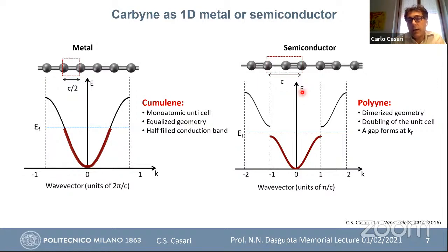In the other case, you have the possibility to have an alternation of single, triple, and so on bonds in a sort of dimerized chain. Now you have two atoms per unit cell, and by solid-state physics reasoning, you can see that a gap will open here, and you will have a completely filled valence band and a completely unfilled conduction band, giving rise to a semiconductor. So we have two possible ideal structures, one leading to a metal and one that should be a semiconductor. Okay, and this could be quite interesting also for electronic applications, as I will show you later.